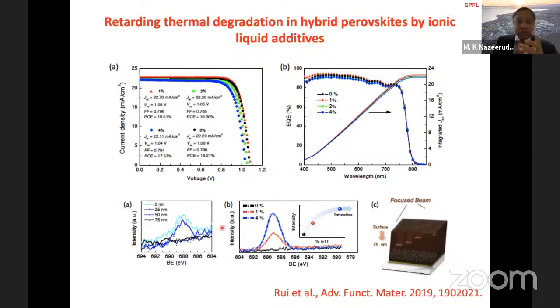Now we took one perovskite grain with focused ion beam. You can treat the surface from the top to bottom, and you can see from 0 nanometers, we have a significant amount of fluorine up to 25 nanometers. But the moment we go up to 50 nanometers, the fluorine is not there. So let me explain what is happening.